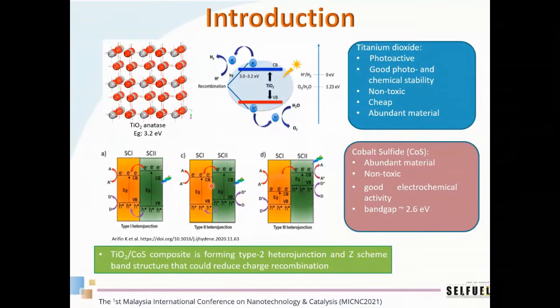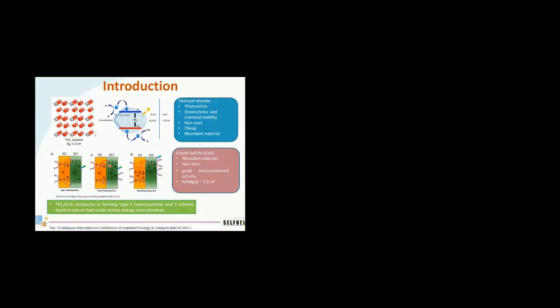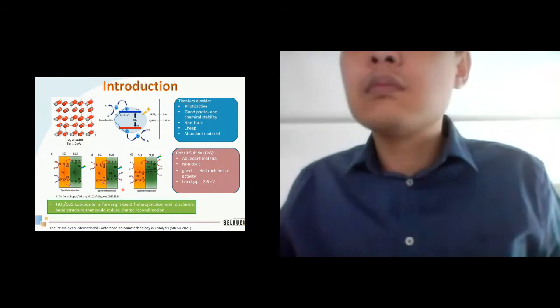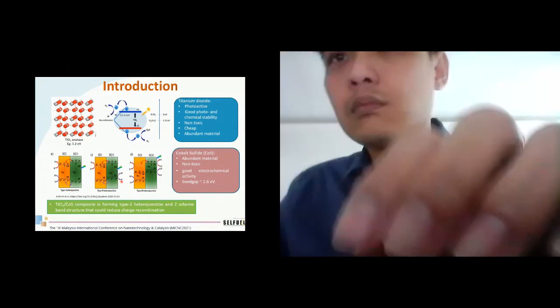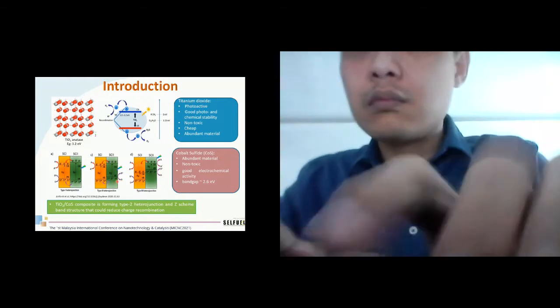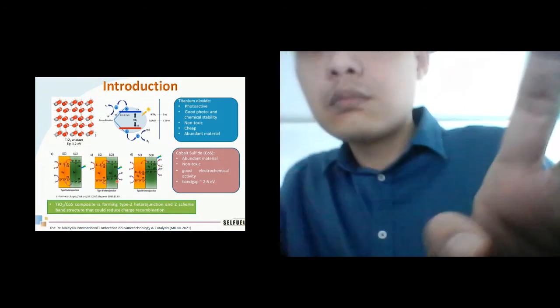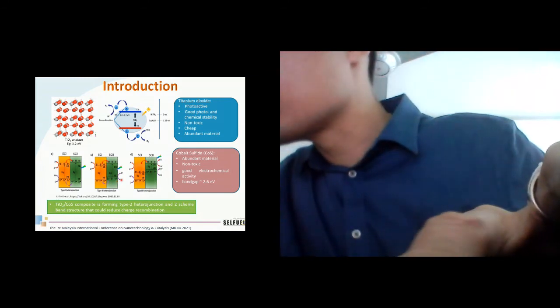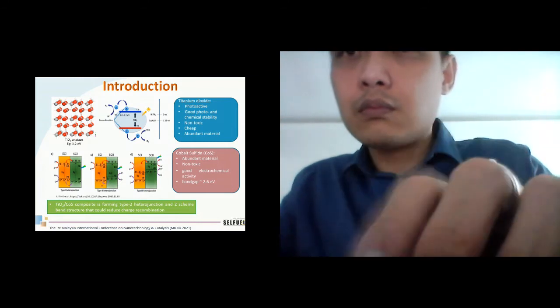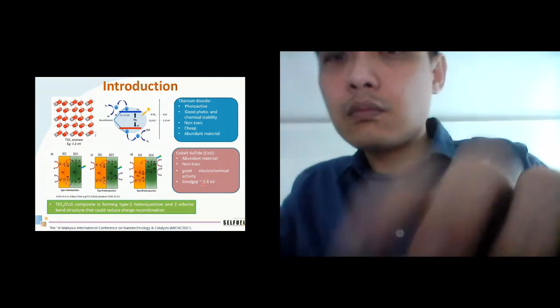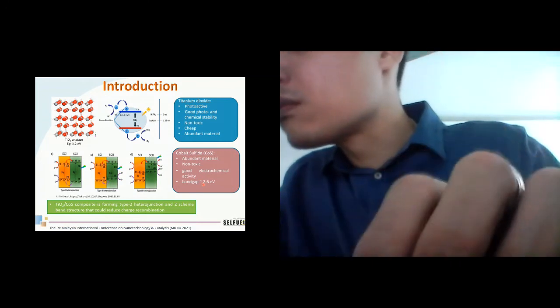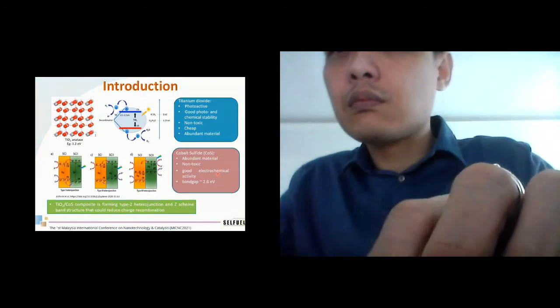There are a few methods to overcome the wide bandgap problem. One of them is by adding a co-catalyst. The presence of a co-catalyst is not only to conduct the reaction, but also to form a heterojunction band structure. A suitable heterojunction is supposed to reduce the charge recombination. In this study, we evaluate photocatalytic water splitting performance by using a TiO2 CoS composite. Why did we choose CoS? Because CoS is an electrochemically active material, cheap and non-toxic compared to other carcinogenic metals.